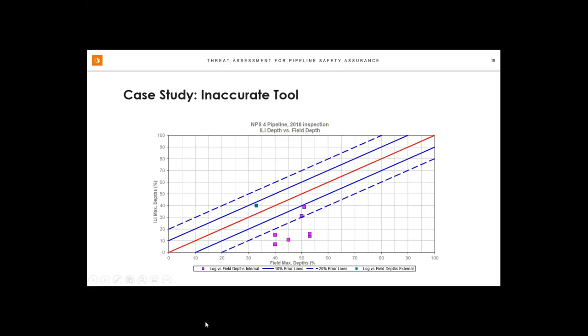The owner operator in this case did request a regrade of the ILI data, but even after they did so, we had very little confidence that that data was actually accurately reporting the state of the pipeline. And so we in essence had to discard that data and do a completely different assessment on this pipeline based on internal corrosion risk factors. We wound up doing a complete overhaul of the internal corrosion mitigation program, increasing the pigging frequency, introducing a biocide into the system, and installing real-time monitoring sleeves. And this wound up being a success story. We were called back a few years later to look at the same pipeline, and we determined that the internal corrosion growth rates in areas where corrosion growth had previously been observed to be occurring had dropped to pretty much nothing.